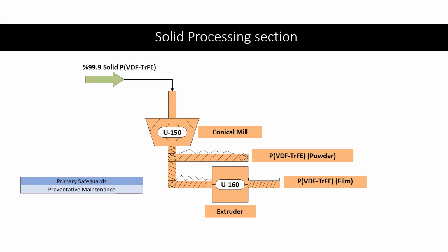When the milled powder is fed into the extruder, as you can see is the last unit operation in the plant, it is melted through a heated barrel and then subjected to a high pressure and shear forces, which will homogenize the material. The molten polymer is then directed through a narrow die, which will shape the polymer into a thin film. And the film is finally quenched and solidified and then cut into sheets as the final product. This extrusion process will take approximately 15 minutes to complete.